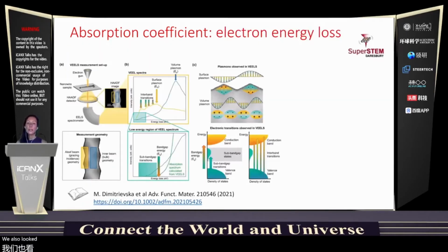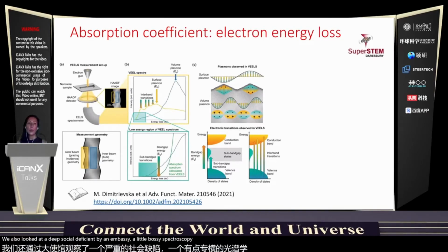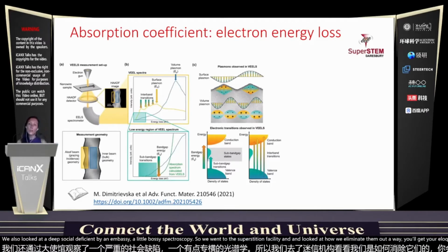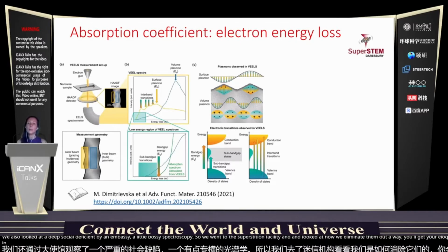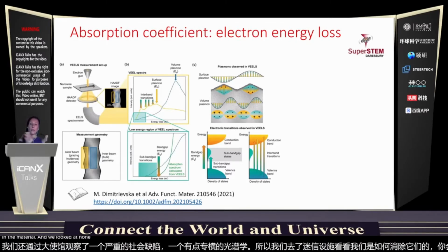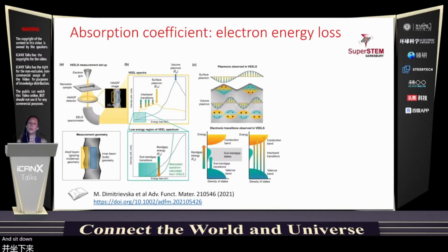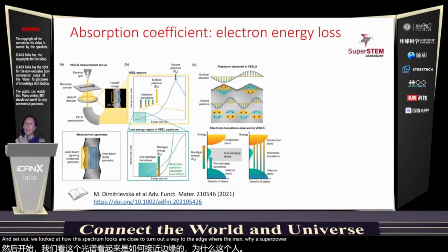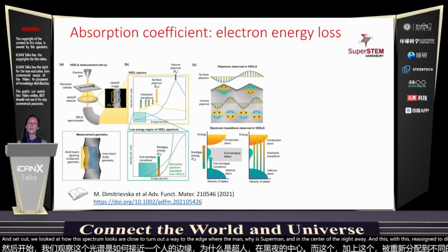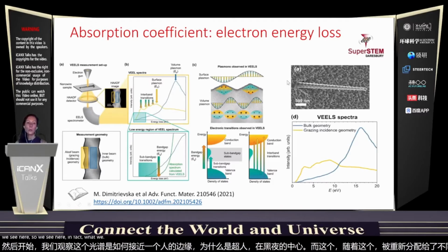We also looked at the absorption coefficient by electron energy loss spectroscopy. So we went to the SuperSTEM facility and looked at how we illuminate the nanowire with electrons, and we look at the energy loss of these electrons in the material. And we looked at nanowires that have this zigzag shape, and we looked at how this spectrum looks close to the edge where the nanowire is super thin, and in the center of the nanowire. And with this, we excite different kinds of plasmons and different kinds of transitions. This is the nanowire we looked at.